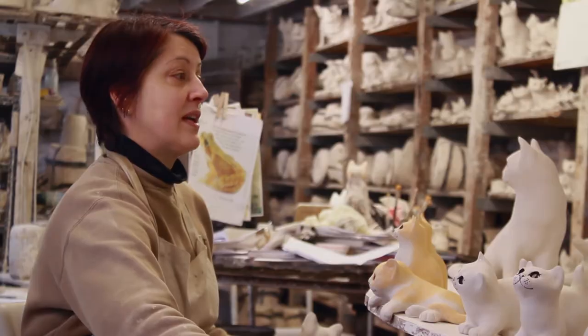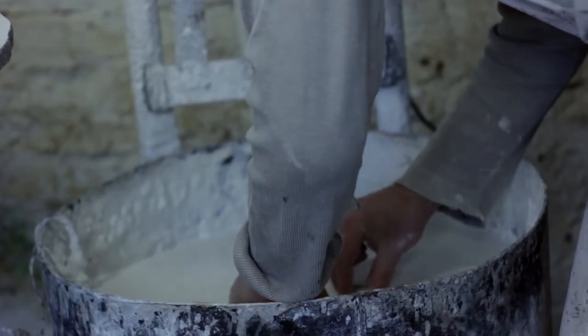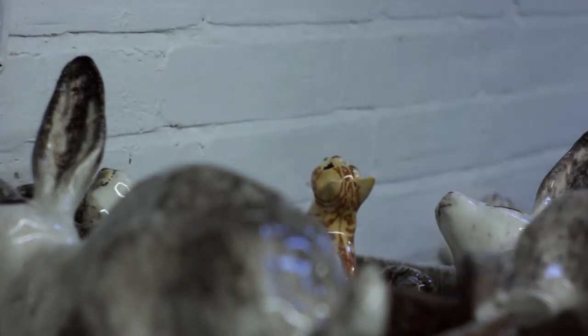The ground colour is put on and then glaze is sprayed on before the patterns are applied. They're then dipped in the glaze which will become the clear glass coating at the end of the process. They're then put in the kiln, which takes about two days — about eight hours of heating up and the rest is cooling. If you cool them too quickly they'll shatter. Once they're cooled and taken out, they'll have our unique handmade glass eyes fitted — eyes we make ourselves from stained glass — glued and fitted to give the finished cat.